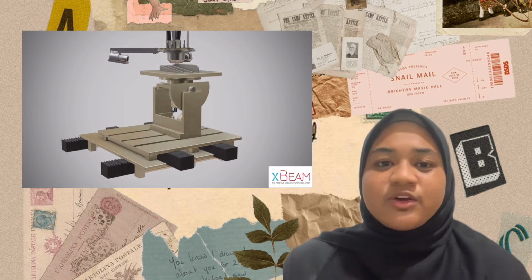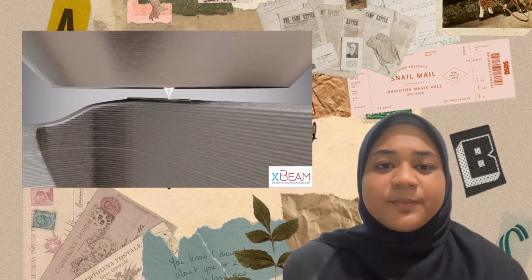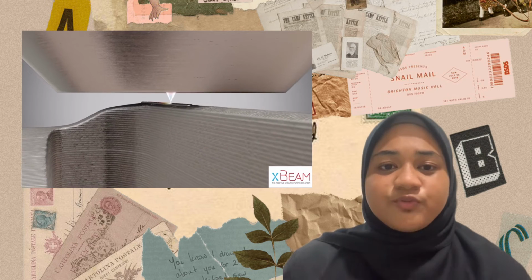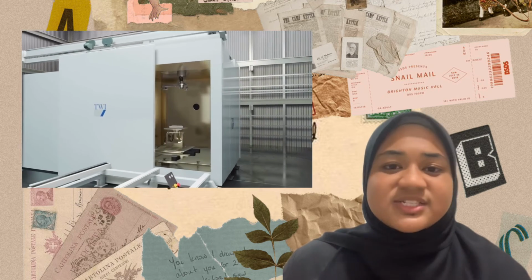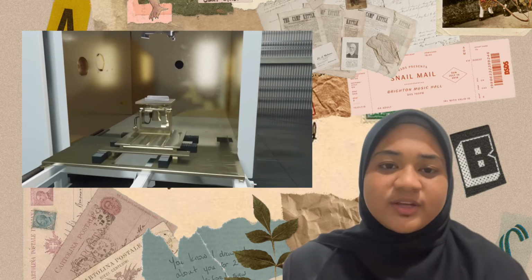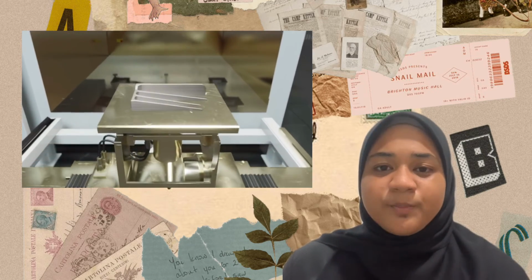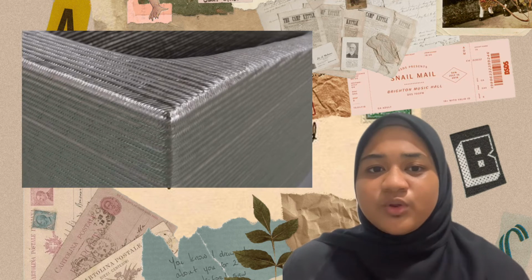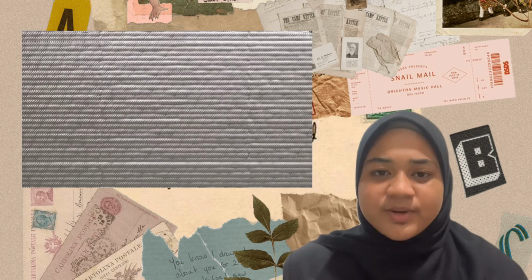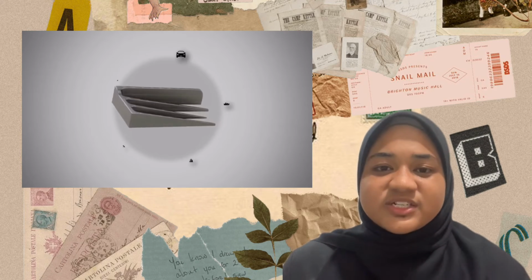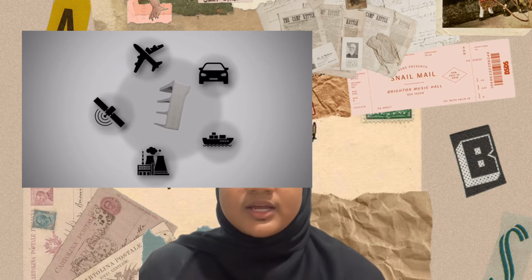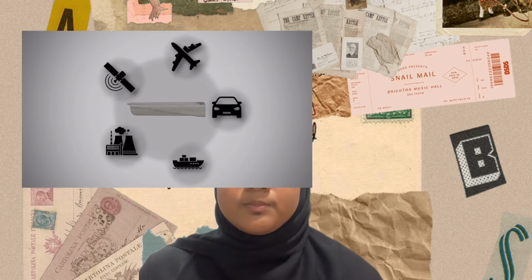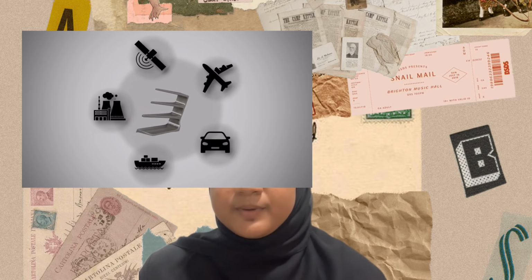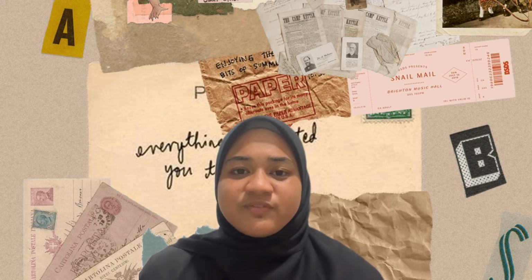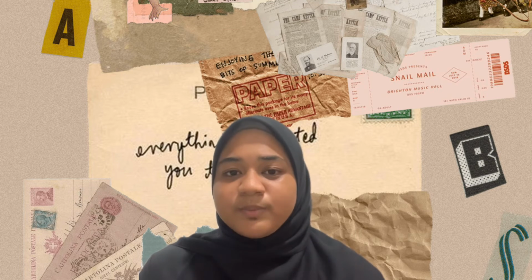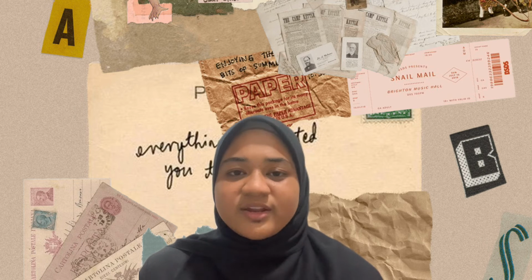Next is the printing process. First, for pre-printing, before the printing process can begin, the powder bin is filled with the desired metal powder. Once that's done, the powder bin is placed into the 3D printer and the internal pressure is set to around 0.001 mbar. Believe it or not, that's around 1 million times less than atmospheric pressure. When the desired pressure is achieved in the build chamber, the electron beam is fired up, heating the build platform to high temperatures. For example, titanium requires 600 to 700 degrees Celsius. After the build platform is heated, the printing process can finally be started.